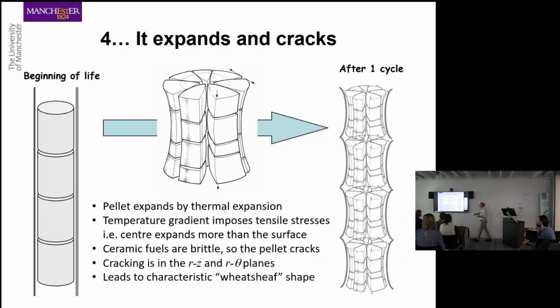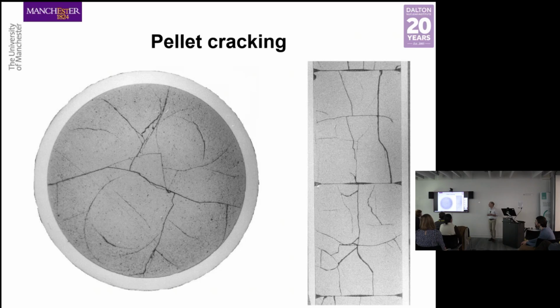It cracks. And it cracks in a pattern that looks vaguely like this. So we expect to see these radial cracks, and we expect to see these circumferential cracks on this sort of r theta plane as well. Does it really do that? Well, it depends on your imagination. So here are some micrographs of cracked pellets. If you stand back far enough and squint at it and sort of say, oh, well, yeah, you can kind of see some radial cracks coming out here. They're not quite like the neat pizza slices that I showed on the previous diagram, but it does happen. It does happen in broadly the same way that the theoretical models would predict.